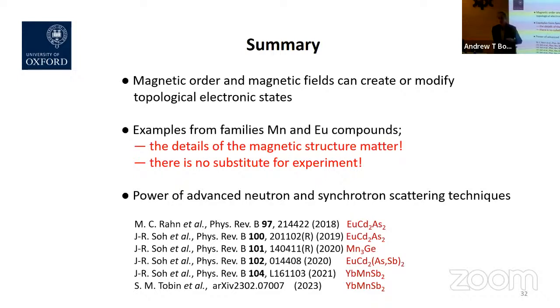The anisotropy is very small, just on the order of 1 millielectron volt, which is kind of the resolution limit of ab initio calculations. But yes, it comes from very weak spin-orbit coupling, relativistic effects, as you say. It's not really relevant for the band topology, because that's on a higher energy scale, but it's important for determining which direction the spins are pointing.